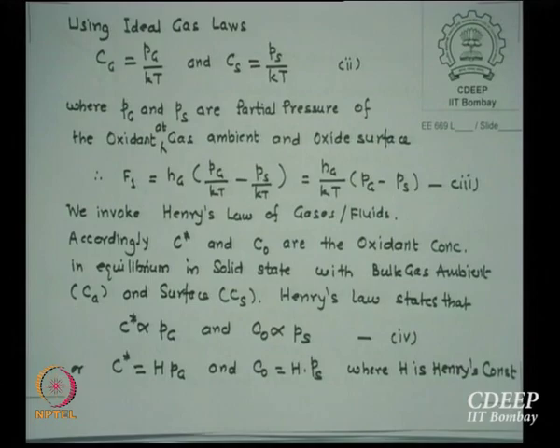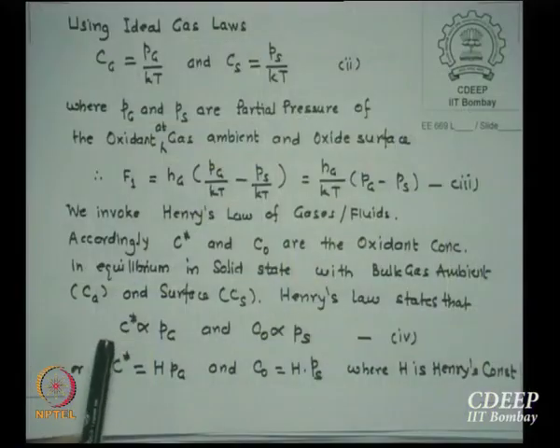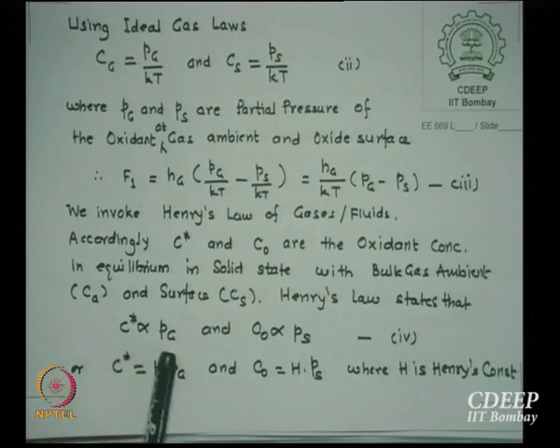We invoke Henry's law for gases and fluids. There is a Henry's law which relates the partial pressure to the solid state concentration. According to Henry's law, C star, which is the equilibrium oxidant concentration in solid state, is proportional to the partial pressure in the gas stream. Similarly, C0, which is at the surface of SiO2, is proportional to the partial pressure at the surface, which is Ps. And there is a constant associated with this equilibrium, which is called Henry's constant. So C star is H times Pg, C0 is H times Ps, where H is called Henry's constant. So now you can see I have a relationship with C star and C0 in terms of Pg and Ps through Henry's constant. So I can use these two equations to go back into equation 3 and find the flux F1.